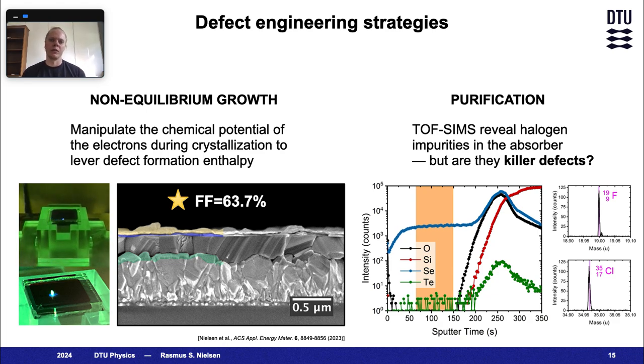Now, another thing we are looking into is whether or not halides could play a detrimental role as killer defects. This is motivated by time of flight SIMS measurements, where we clearly observe both fluorine and chlorine in our absorber.